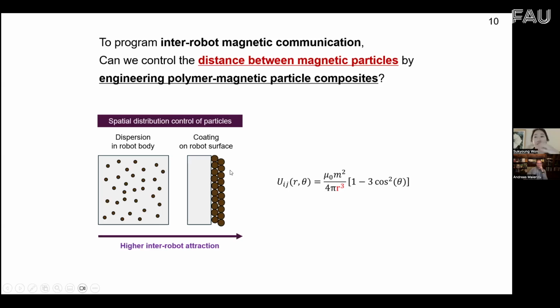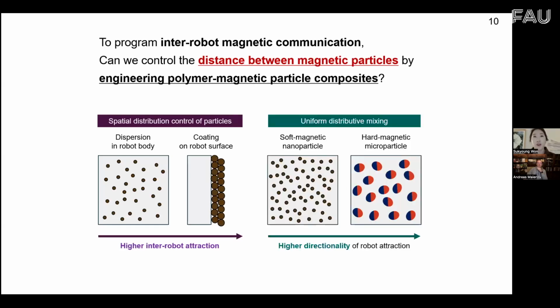attraction. That means the surface-coated magnetic particles can enhance the inter-robot interactions and promote the self-assembly between the multiple robots. And also, besides the spatial distribution, we can also consider the magnetic properties of the particles, such as the soft magnetic or hard magnetic properties. This magnetic anisotropic profile in the robot allows the programmability of the assembly directions.